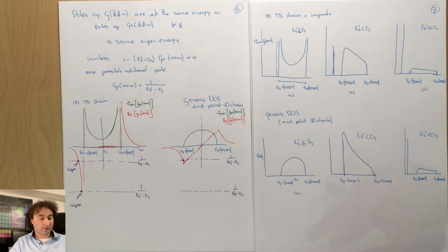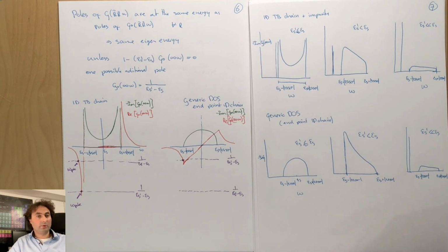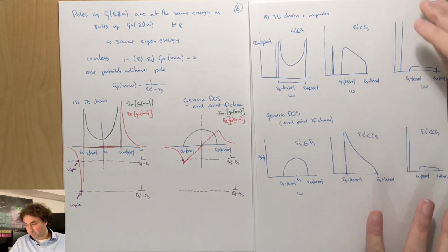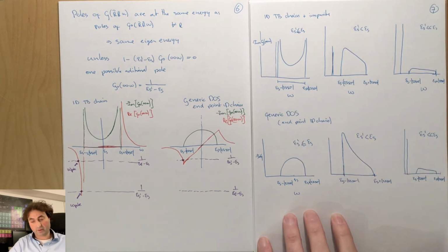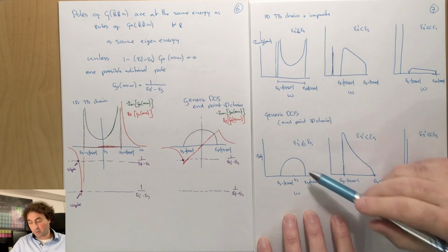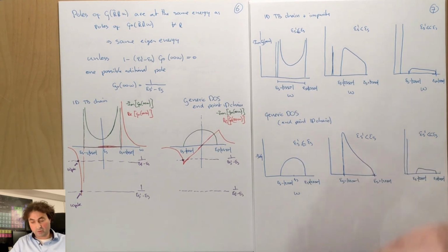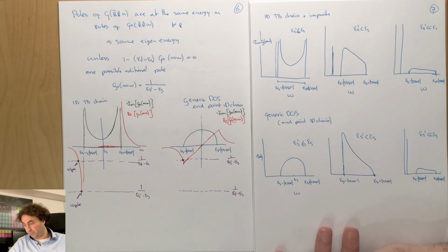With this we can already understand why when we have silicon you normally wouldn't dope it with nitrogen, because the impurity potential for nitrogen is too large and therefore not electron doping the system, but making localized impurity bound states in that system. So for semiconductor physics you're looking at dopants where the impurity potential is so small that you're basically just shifting the chemical potential and not creating bound states.